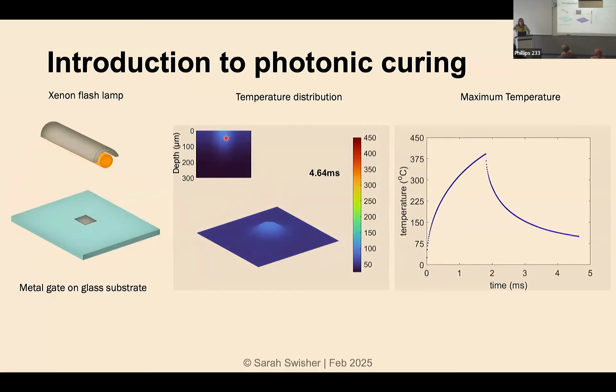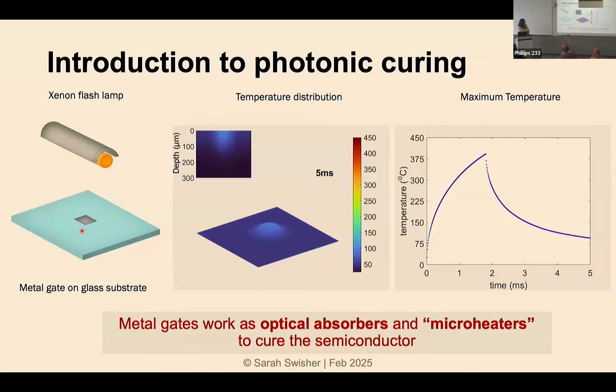So it's heating up very rapidly, but then as soon as the light turns off, it begins to rapidly cool, and that heat is sucked away into the substrate. And the temperature that you reach here is going to be a function of the absorption properties of these materials and also the thermal conductivity. But the key point that I want you to take away from this is that what we have here is a metal gate that's working as an optical absorber. And then essentially it's like a little microheater where we're only going to heat the area on top of that metal gate. So we get this nice sort of self-aligned aspect of this work as well.